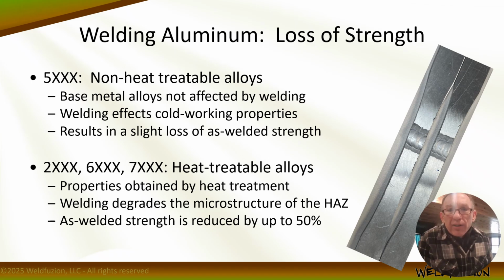Now let's talk about the fact that aluminum alloys lose strength when arc welded. In heat-treatable alloys like 2000, 6000, and 7000 series, the heat of arc welding causes something called precipitate growth, where the alloying elements collect at the grain boundaries and reduce strength in the heat affected zone. In the case of 6061 aluminum in the heat-treated condition, all of the alloying elements have been dissolved and evenly distributed through the aluminum. That's a process that heats the material and then quenches it after time to lock those precipitates in position, right? So that they don't migrate to the grain boundaries upon slow cooling.